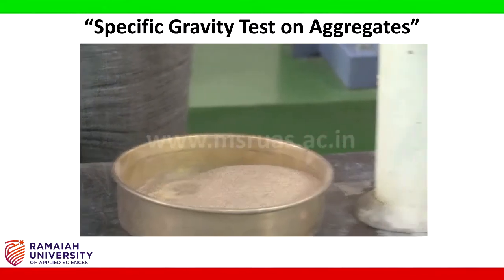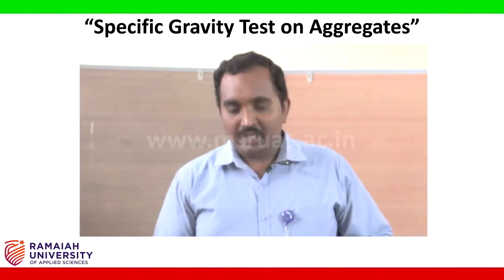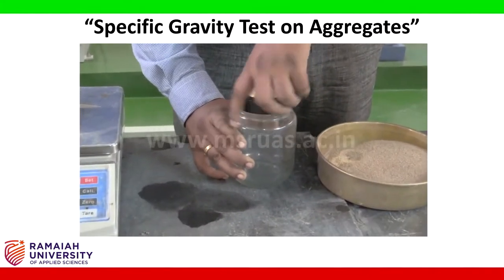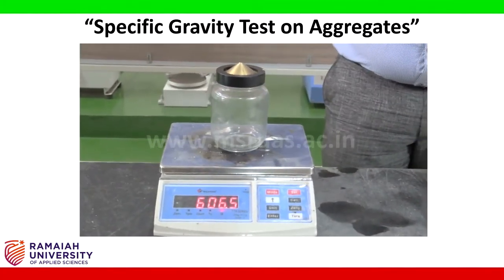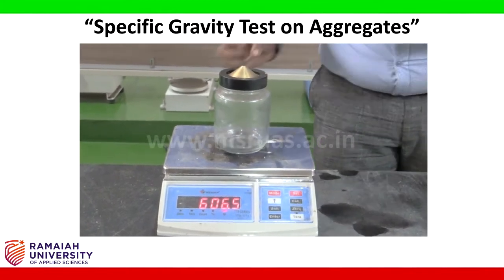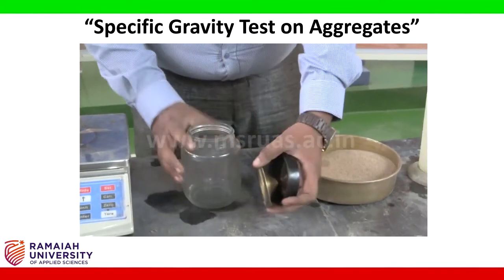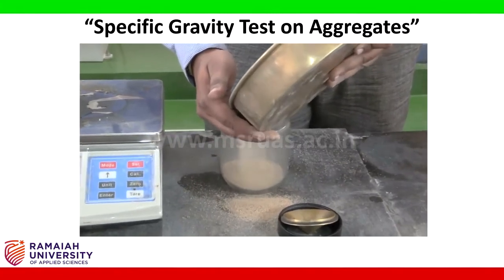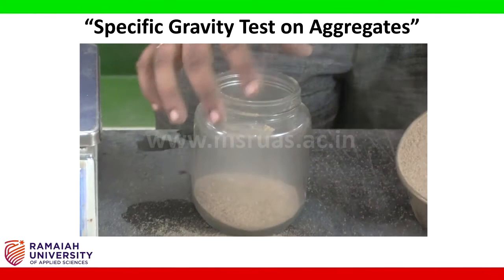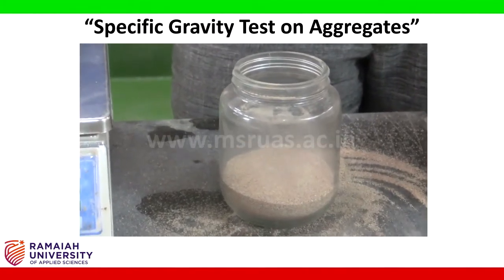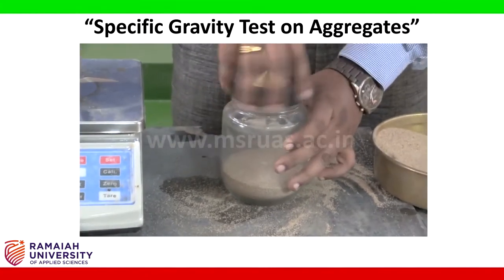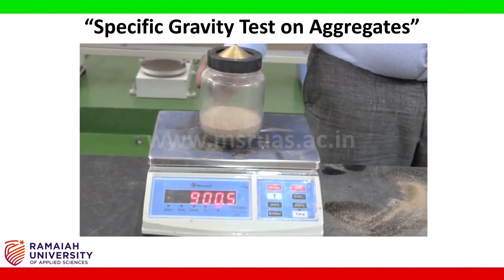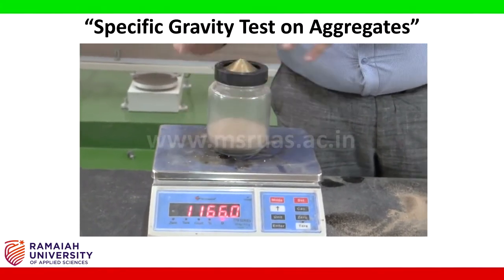I have taken some quantity of sand and water. First, I am going to take the empty weight of the dry pycnometer — this has to be oven dry. I am noting this weight as W1 grams. Next, I am going to add one third of fine aggregate into the pycnometer. Approximately one third of sand is added. I fix the collar and cap back and take W2, which is the weight of pycnometer plus sand.